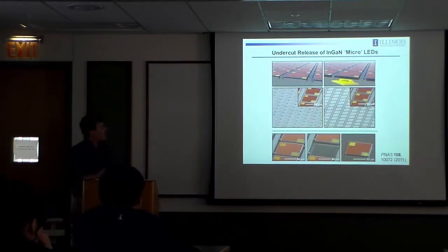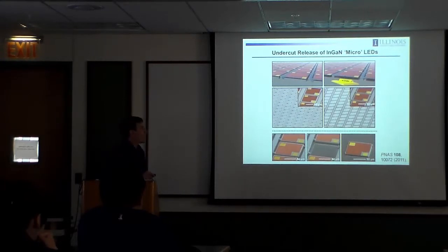So in this case, instead of using aluminum arsenide as a sacrificial release layer, what we do is we grow indium gallium nitride on a silicon wafer that has a 1-1-1 orientation. You can do that. You can create high quality InGaN that way. And then the silicon wafer with that orientation has the appealing property that it etches anisotropically in a solution bath of potassium hydroxide. In particular, the etching rate along this crystallographic direction is about 500 times faster than it is along that direction or down into the depth.